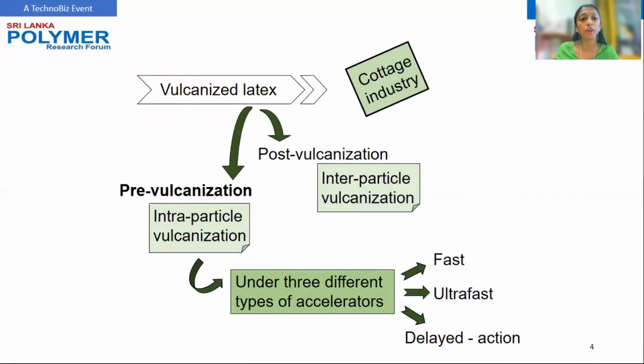Pre-vulcanization, which gives intra-particle cross-linking, has high latex stability and is simple to use compared to post-vulcanization, which gives inter-particle cross-linking. So, pre-vulcanized latex produced out of cream latex can be prepared in small quantity at home even, but centrifuge latex cannot be produced likewise. In this scenario, this research study was carried out targeting cottage industry, targeting manufacturing of products with